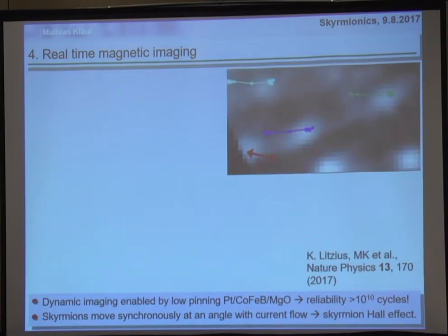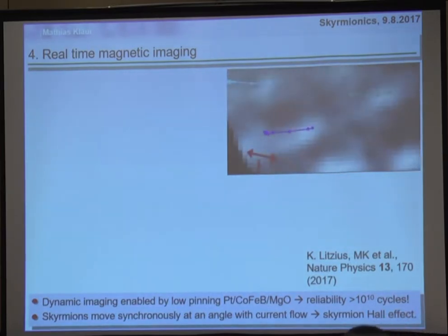What we see sometimes is that skyrmions cluster together and move together very rigidly, so there must be some attractive short-range potential interaction. That's something we're trying to find out at the moment by playing billiards with the skyrmions. We shoot one skyrmion onto another and see how they get scattered. But it's an extremely difficult experiment. We're trying to measure the scattering factor of one skyrmion and another.